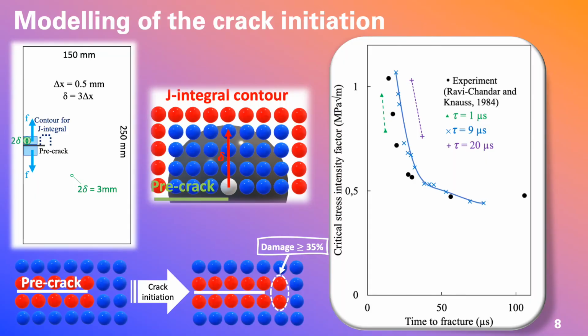In the present work, crack initiation tests were modeled in a similar manner as it was done in the experiments of Ravi-Chandar and Knauss. For this study, a Homalite 100 specimen with sizes of 250 mm in height, 150 mm wide, 3 mm in thickness with a pre-notch length of 25 mm was found to be appropriate, as the reflected waves from the boundaries don't reach the crack tip during 80 microseconds. Discretization size was taken 0.5 mm and horizon size was taken 3 times greater than a discretization size.